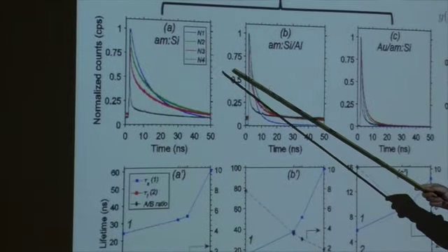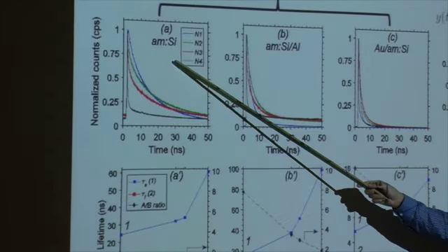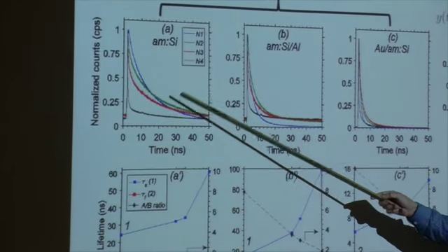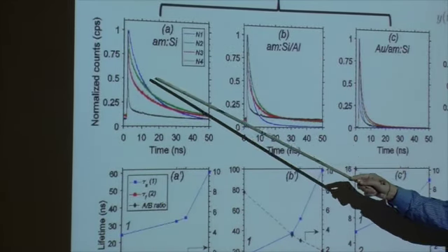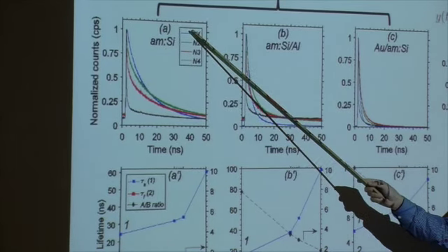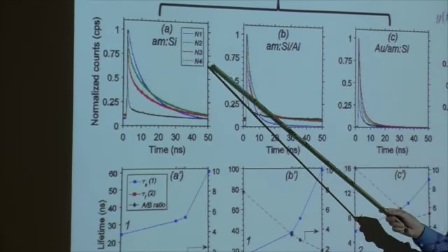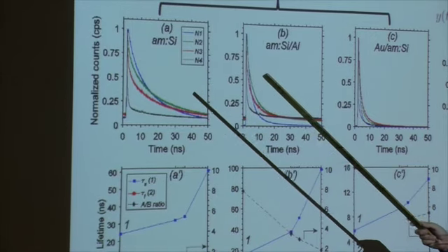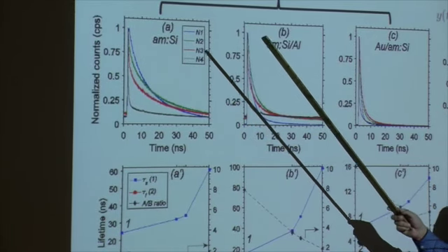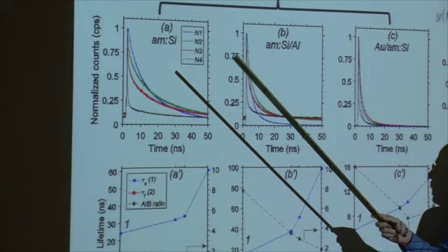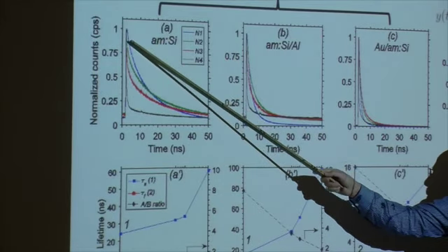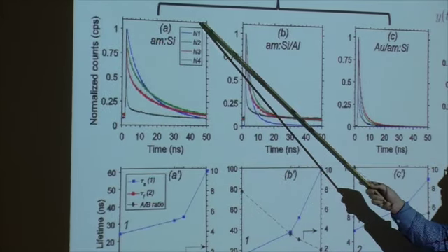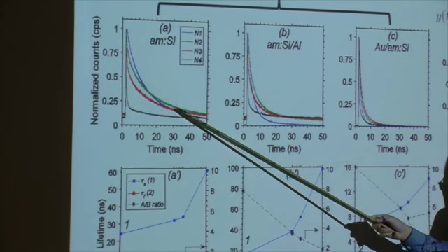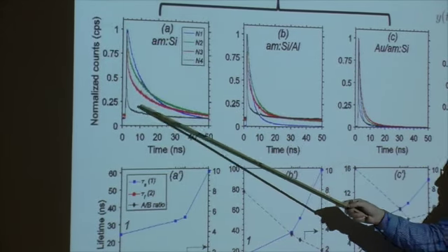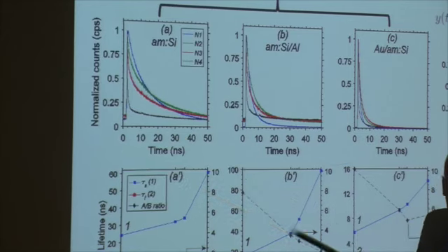I have to go a little bit fast, but here you can see the decay of quantum dots on silicon. N1 is an ensemble of quantum dots, many quantum dots, and N4 is the single quantum dot limit. So remember, N1 is many quantum dots, N4 is a single quantum dot. You can see that the emission of the quantum dots when it is an ensemble lasts longer than the emission of the single quantum dot. A single quantum dot decays very fast.